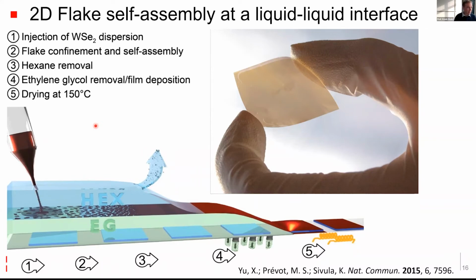In fact, there is. This is quite important because we've tried many different coating methods for these nanoflakes, and one that we thought might work would be sort of more the Langmuir-Blodgett or the liquid-air-based interface. We can float our dispersions on top of a liquid, but as that solvent that the material is dispersed in evaporates, it gives time for these flakes to aggregate. In fact, when we use the liquid-liquid interface, the liquid here that's in the dispersion goes quickly. It's soluble in both the top and the bottom layer, but the flakes are not dispersible in the top or the bottom layer. So it's really about that kinetics of getting that dispersion solvent away from the interface very quickly, away from the flakes very quickly. And that leaves the flakes to minimize their energy and stay at that surface, and will not give them time to find a partner and aggregate. So we found that to be really important.